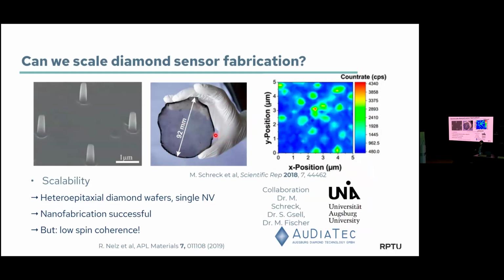And why is this diamond so huge, or why is it so hard to make such a huge diamond? Well, normally if you grow diamond, you need a diamond for a substrate. So when you make this artificial diamond, you need some other diamond as a substrate. But because this other diamond is tiny, your diamond cannot be large. And what they have done here is so-called heteroepitaxy. So they're growing diamond on a non-diamond substrate. This is how they can crank it up.